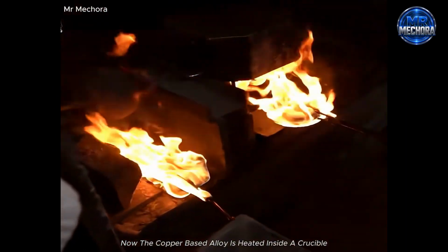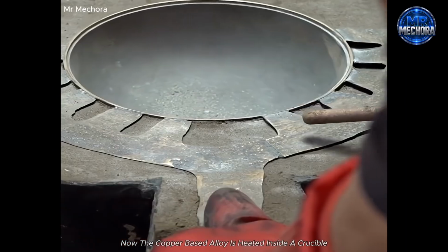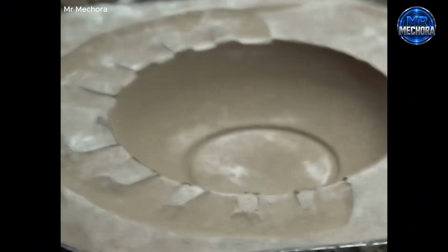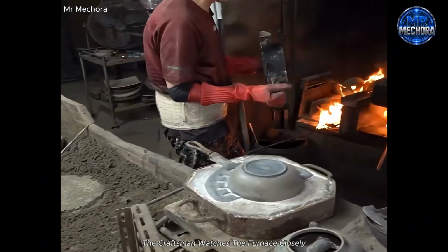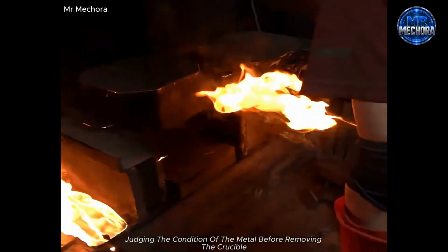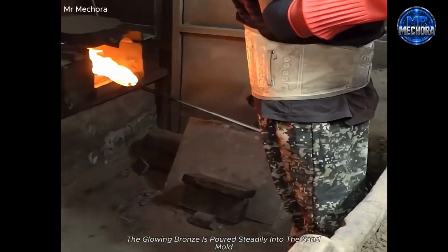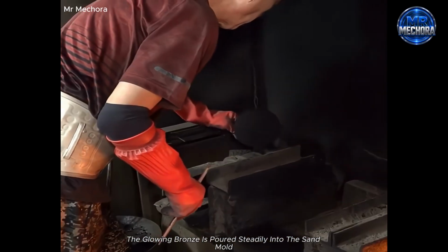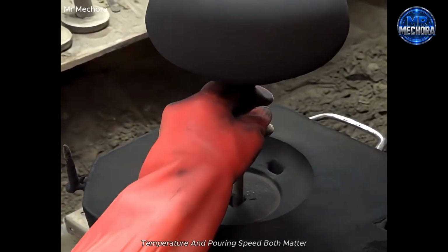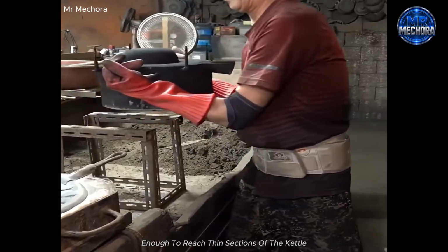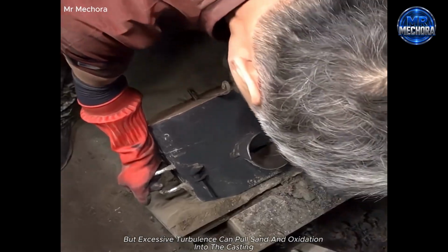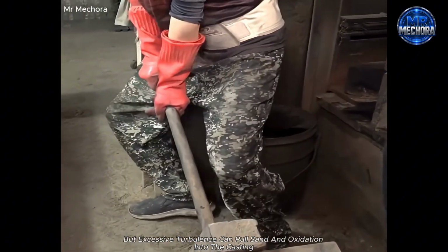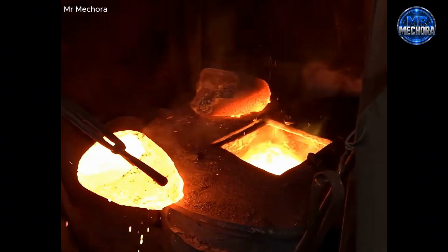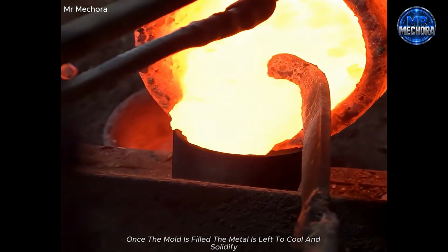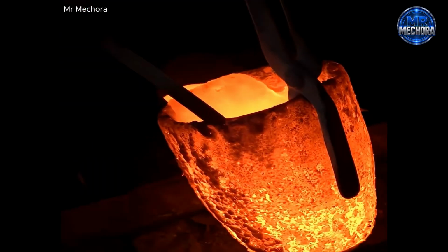Now the copper-based alloy is heated inside a crucible until it becomes fully molten. The craftsman watches the furnace closely, judging the condition of the metal before removing the crucible. The glowing bronze is poured steadily into the sand mold. Temperature and pouring speed both matter. The metal must remain fluid enough to reach thin sections of the kettle, but excessive turbulence can pull sand and oxidation into the casting. Once the mold is filled, the metal is left to cool and solidify.